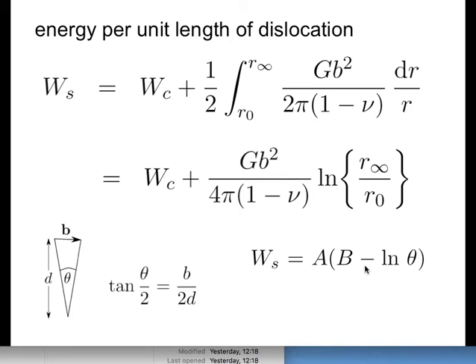Okay, the minus sign appears because R infinity is equal to d, the spacing between the dislocations, because they compensate for each other's strain field. And d is proportional to 1 upon theta, and therefore we have the minus sign in front of the log. Okay? Right, so that's the energy per unit length of a dislocation in an array.